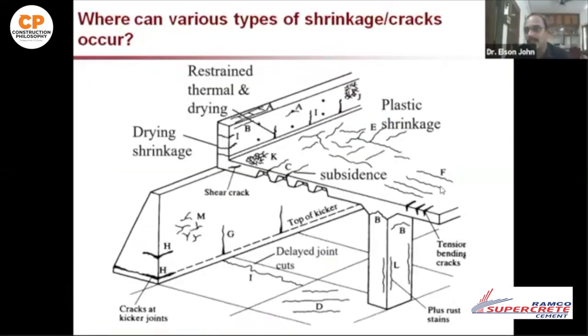Then freeze-thaw resistance and thermal cracks. So this is a very interesting figure. We can see the different types of cracks in a particular structure and where they occur. Where these plastic settlement cracks occur, there will be ring-like reinforcement in the longitudinal as well as horizontal direction, so the cracks can occur here. Again, there is reinforcement, and below that part of the reinforcement, concrete can settle. So again, we have the plastic shrinkage cracks. This is also plastic shrinkage cracks. These cracks are due to tension, because of the loading, tensile cracks can propagate.